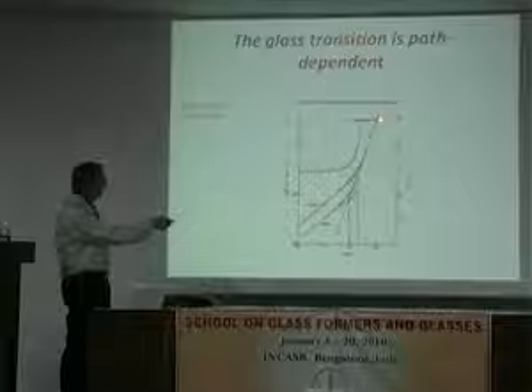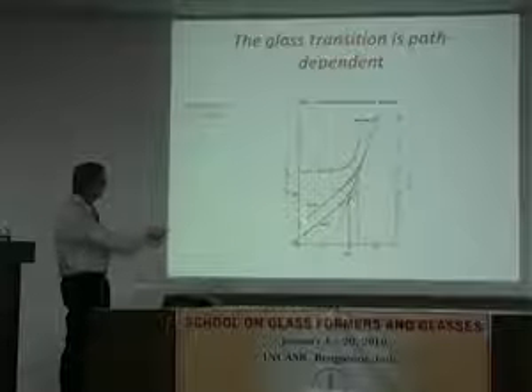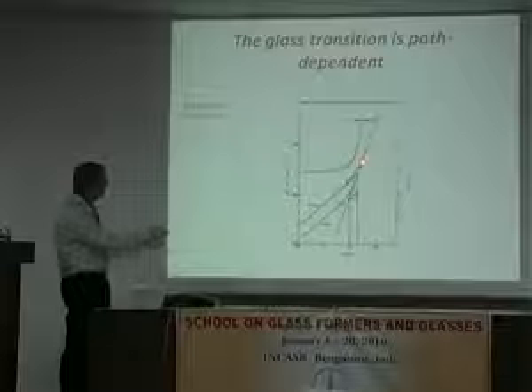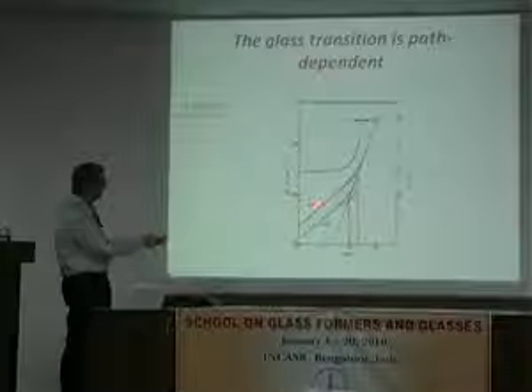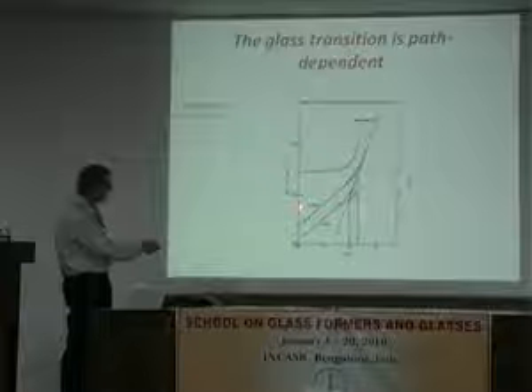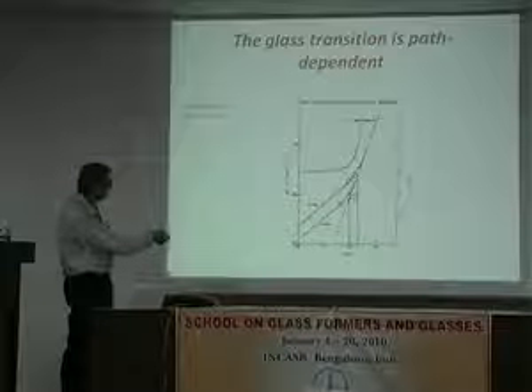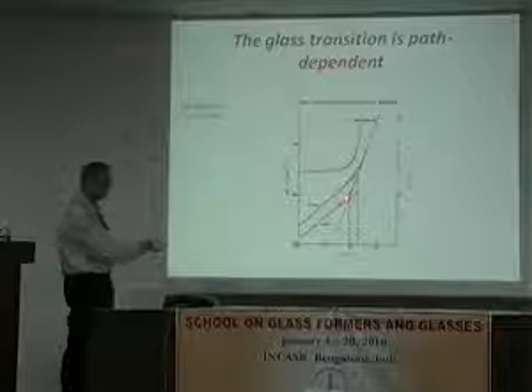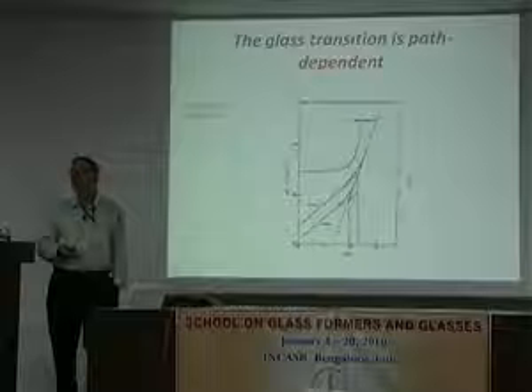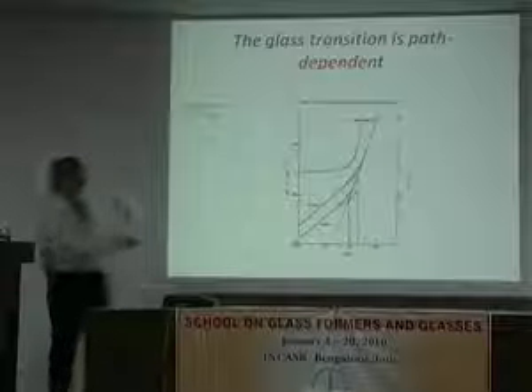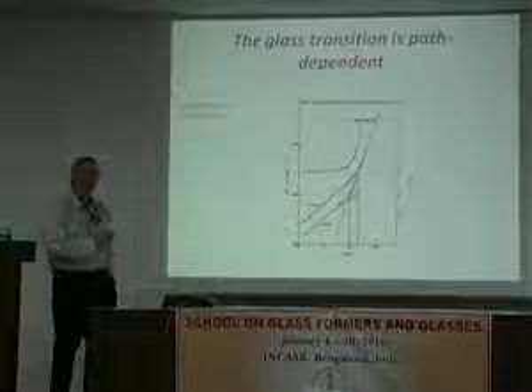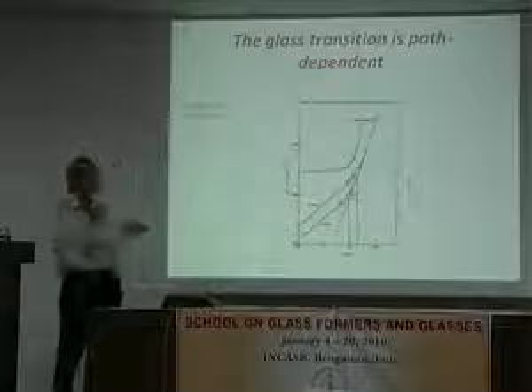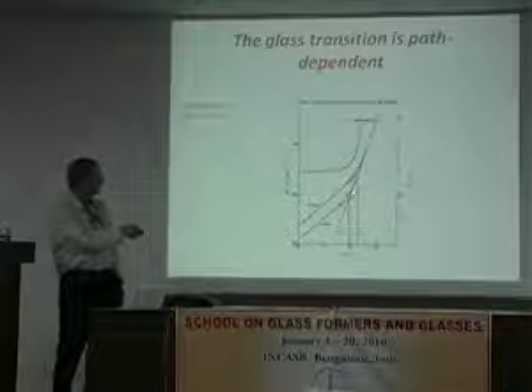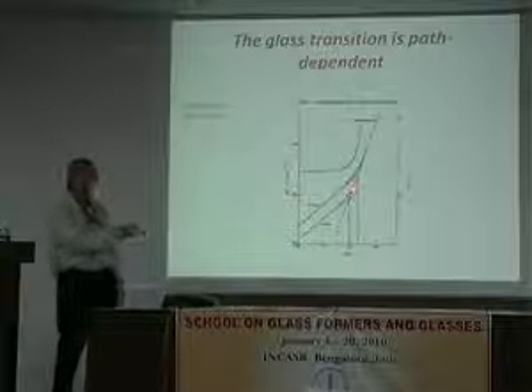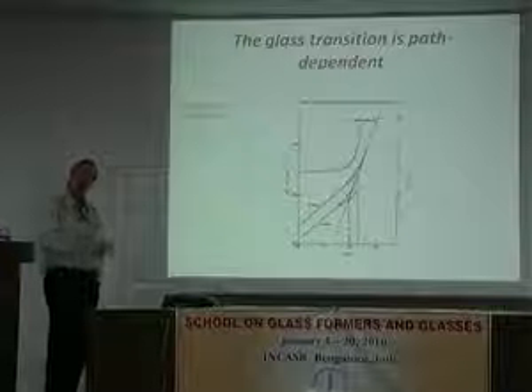And what Kovacs showed was that, of course, if you change the speed at which you do this, and this is actually each data point represents a jump that takes 0.02 hours. In this one, each data point was 100 hours apart. Okay, so these are very long experiments, right? Something to keep in mind as you worry about doing your computer simulations. Here was somebody doing experiments. Each one of these data points represents waiting 100 hours. Okay, so a little bit of patience, you know.